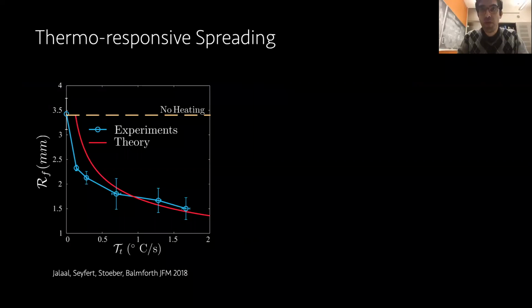These experiments actually made us answer one classic question in solidifying spreading droplets, which I will come to. So two main things we found out. First, this is an effective technique to control the spreading of a droplet on a surface. What I'm showing here is the final radius on the y-axis as a function of heating rate. You heat the surface faster, you get a smaller droplet. And the cool thing about these polymers is that you can do the cooling, so you can reverse the process, and then they become like a Newtonian fluid again, and you can wash them off fully. So you can use it as a smarter way of printing and removing, printing and removing, if you want to use it in 3D.